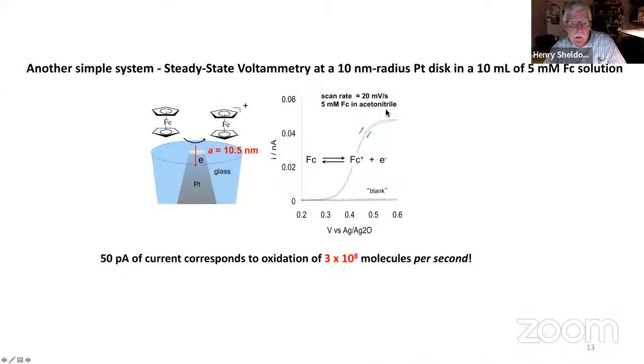Here's another example. This is from my lab. This is a real example looking at the oxidation of ferrocene to ferrocenium in acetonitrile solution using a 10 nanometer radius electrode. And here's the voltammetric response. You scan out and you start oxidizing ferrocene, and it becomes diffusion limited. And it's a small current. This is about 50 picoamps, the limiting current here. And you say, well, what does that correspond to in terms of the number of molecules being oxidized per second? And it's on the order of 10 to the 8th ferrocene molecules being oxidized per second.